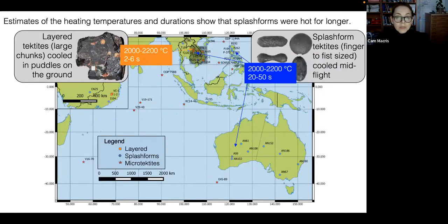Here's just another way to show this information to summarize these results so far. We found that the layered tektites experienced temperatures between 2000 and 2200 degrees Celsius for very short periods of time, just a couple of seconds, whereas the splash form tektites were heated to those high temperatures for longer, between 20 and 50 seconds. The interesting thing, again, is that statistically, all of the splash forms experienced the same thermal history, no matter where they were collected, which is surprising, as we expected that the sample's heating history would vary from location to location.